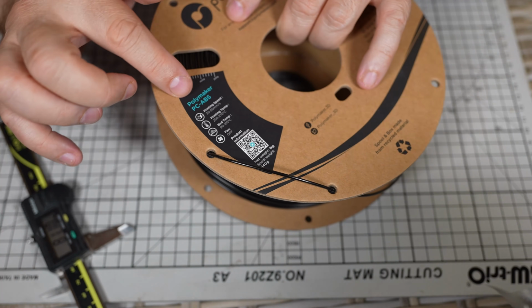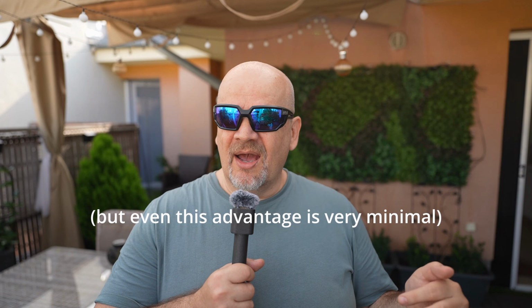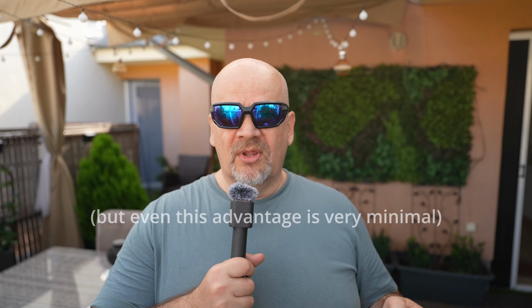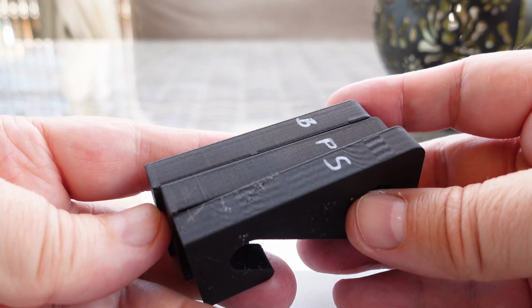And between Stratasys and Polymaker PC-ABS filaments, I think the difference is almost negligible, and I cannot really see the justification of the higher price of Stratasys PC-ABS, except maybe a higher temperature resistance. Earlier with the printing of ABS and ASA, I could see improvement in the print quality, and something happened here, I'm not really sure, because earlier the Stratasys print quality was fantastic, and here I could see that ghosting. So this was my short experience with these two filament types and printings on two different printers.